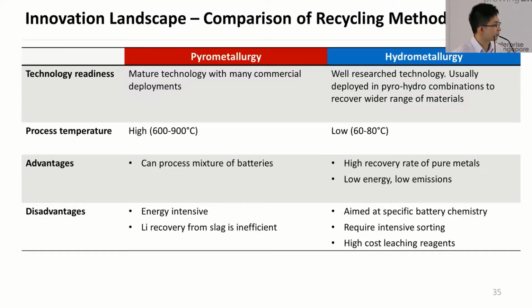And as mentioned earlier, lithium recovery from the slag is rather inefficient because it involves a high amount of leaching acids. While for hydro, it can achieve a higher recovery rate of pure metals. It involves lower energy as well as lower emissions. But this is aimed at specific battery chemistries, so it must be sorted upfront to achieve good quality products downstream. It involves high-cost leaching agents, as you recall, the strong leaching acids. Those are expensive commodities.